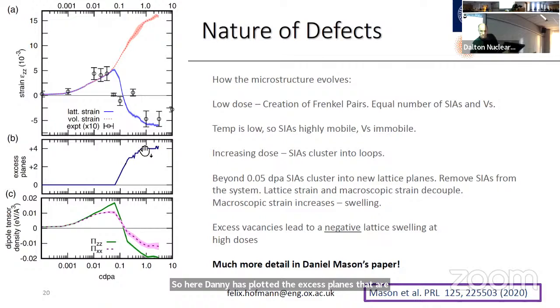Yeah. So we're forming new atomic planes, and it's exactly at this point here that the lattice strain, so the blue strain that we measure with X-rays, decouples from the macroscopic strain that you would measure if you took, say, a ruler to the sample, right? So if you measured the sample with a ruler, you would measure an expansion. But if you use X-rays to look at the lattice, you measure a contraction.